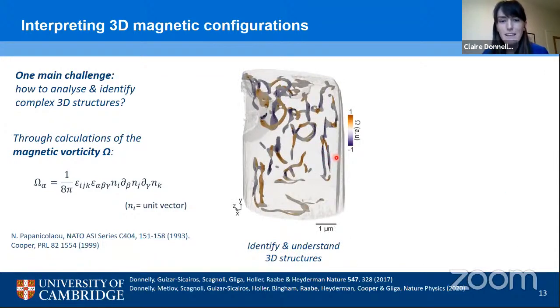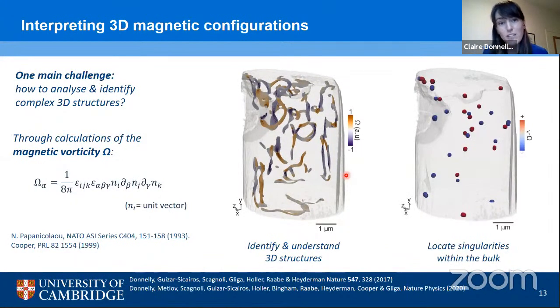You can see immediately that we have a sort of network of tubes which correspond to the cores of vortices and antivortices within our structure. But we can actually go further than this. We can also look for abrupt changes in the magnetic vorticity, which represent abrupt changes in the topology and therefore the presence of Bloch points, by plotting the divergence, so regions of high divergence of the vorticity vector.